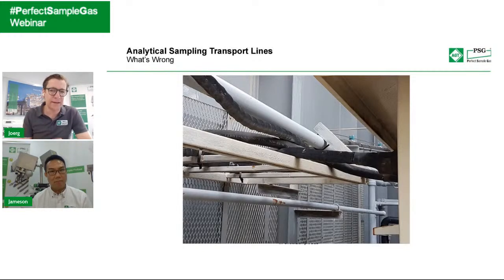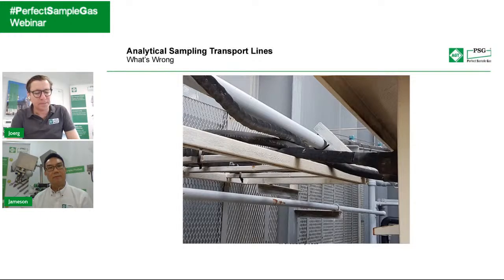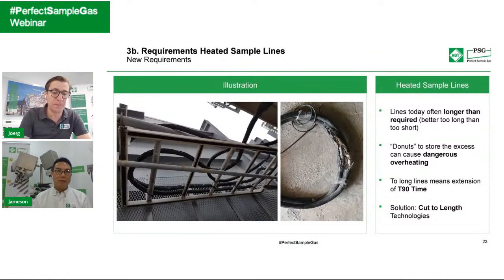I mean, when we talk about quick fix here in the CEM system, I think the layout and the dimension of the tubes, the PTFE tubes inside, also has an effect on the response times, obviously. But if you once decided to go for 8 millimeter outside, 1 millimeter thickness with a 6 millimeter inside tube, it's pretty hard to change this after it is installed, right? And other effects we already touched on, you will probably not see when you choose a high quality PTFE, such as memory effects or any other effects which might come from the line.